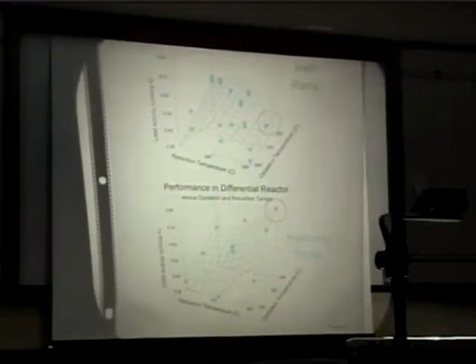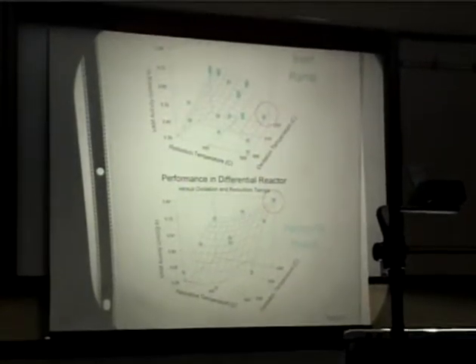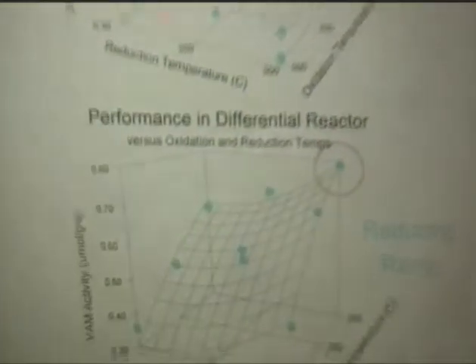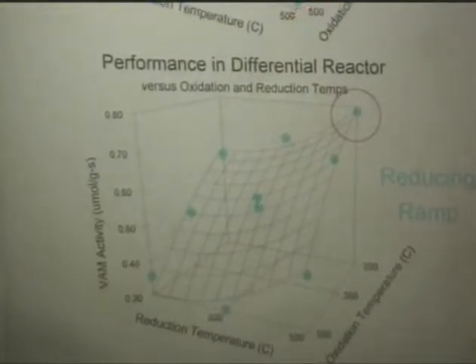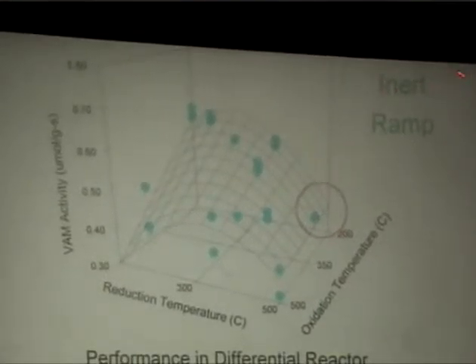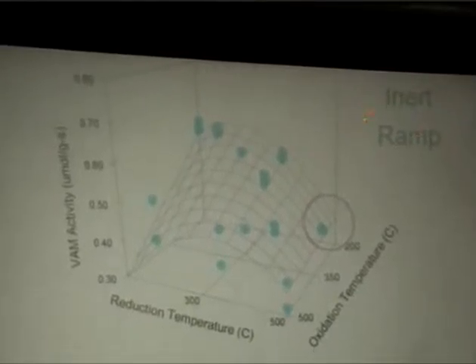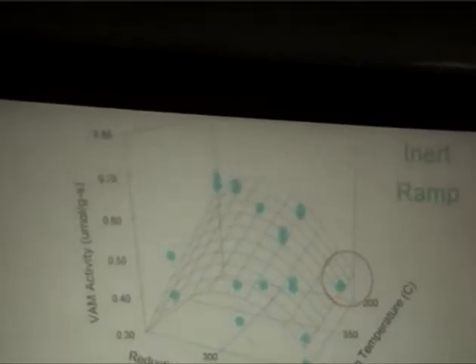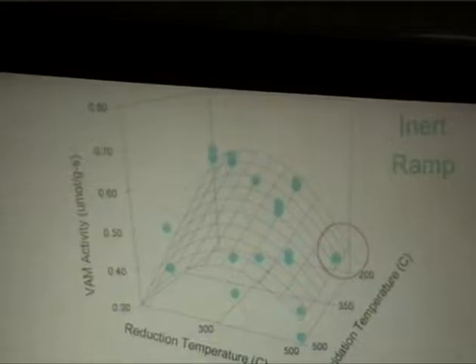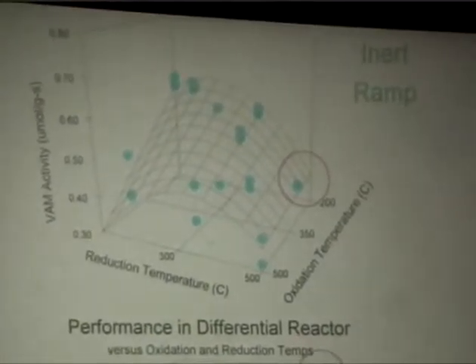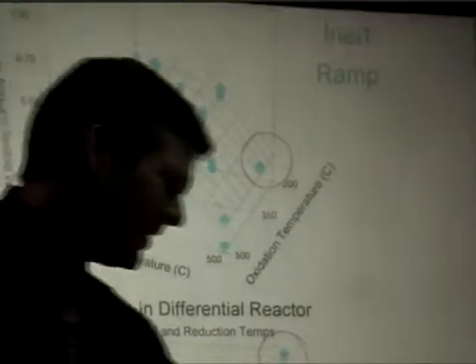So here we have a 200-degree oxidation, 500-degree reduction. We get a very active catalyst if we ramp that temperature in hydrogen. On the other hand, here, when we reduce at 500 after we've oxidized at 200, ramping that temperature in inert, the activity is much lower. And so what we thought is, that's kind of interesting. Can we develop that further? How does that compare to our current catalyst? How does that compare to other folks' catalysts?